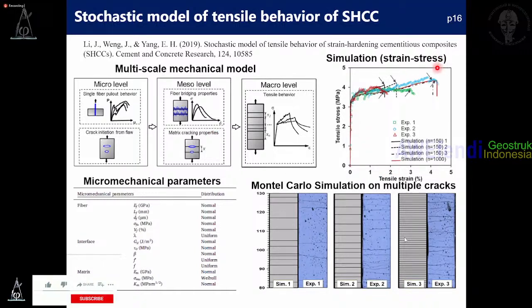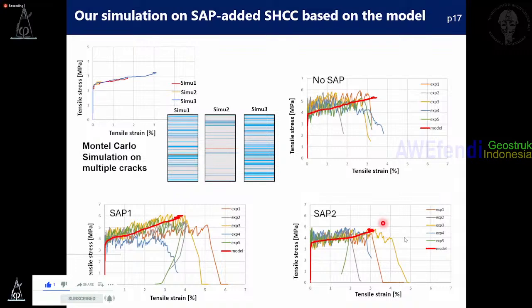So for the strain and stress simulation, they can simulate the multi-crack, the randomness or uncertainty of multi-cracks for the high variation. And we tried to adopt their method, and we represent their analysis like this. So 3 simulations, and you can see in each simulation you have different crack patterns. And then we use it for the 3 cases, no SAP, SAP 1, SAP 2. So the red line is our analysis simulation.